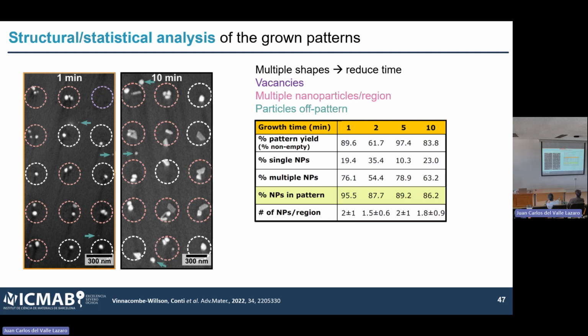Why is that interesting? It is interesting because if you see here, these circles represent the area where theoretically we have our reducing agents. And as you can see, these areas are 230 nanometer in diameter. So theoretically, the particles that we're growing are much smaller than the area. So what this tells me is that once a particle nucleates, it is much more probable for this particle to grow than for another particle to nucleate in the same spot. So the idea here is that if instead of 230 nanometer, I can reduce this to, I don't know, 80, 50, which should be doable using our approach, theoretically we will be able to control the position of the particle better, because now the particle can nucleate at any point in this area. But if I reduce the area, I will control it better.